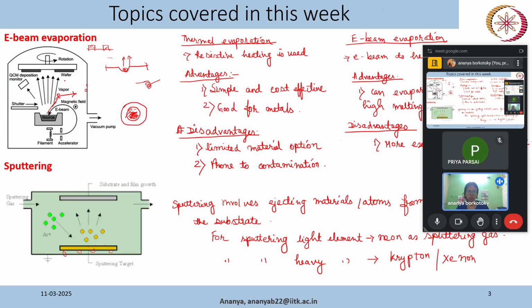So it has a crystal monitor that oscillates at a certain resonance frequency, and that resonance frequency will change if there is some deposition because of the weight. So due to some deposition, the weight of this monitor will change, and the frequency will change, and after some internal calculation, that will give you the expected thickness. Now we have this shutter as well here. Say you want to deposit a 50 nanometer nickel film, then if your monitor is showing your desired value, you can close the shutter and you will stop your deposition.